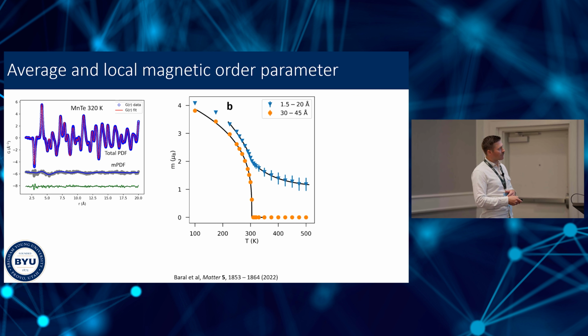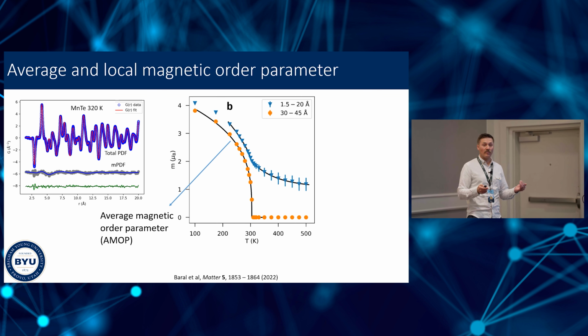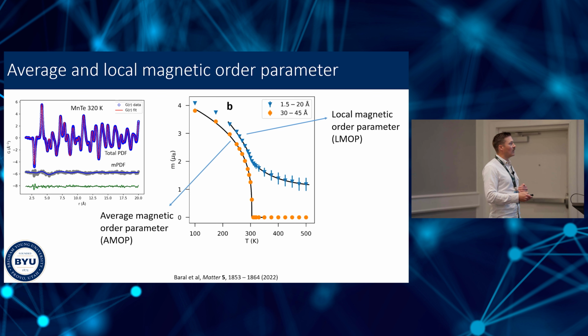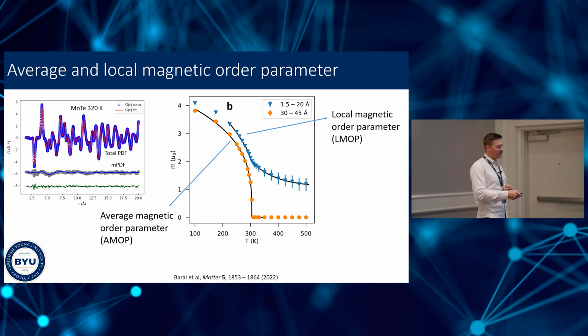On the other hand, if we look at our magnetic PDF data and perform our analysis just up to the first 20 angstroms. Okay, so we're looking on a 2 nanometer length scale. And we fit our magnetic PDF model to the data to get these little wiggles out. Then we can pull out a local magnetic order parameter, which looks a lot different. So here's the local magnetic order parameter, these blue triangles. It does not disappear above the Néel temperature because we still have local correlations present. All right. So this is really highlighting the difference between the average and the local magnetic structure.